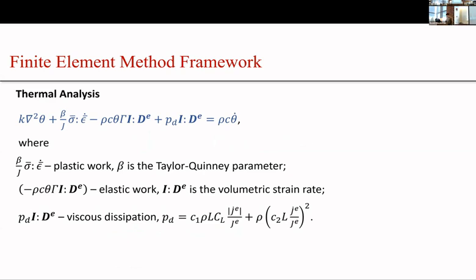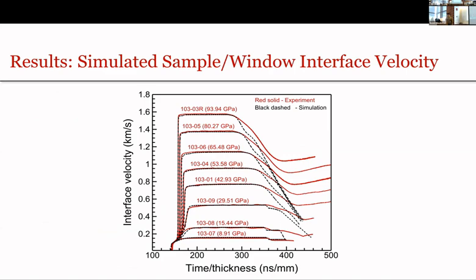So by calibrating the model parameters, we are able to fit the measured wave profile in the transmission wave experiments pretty well, especially in the elastic wave and the plastic wave speed, also the elastic-plastic hardening part and the peak state. There is some discrepancy at the unloading part.